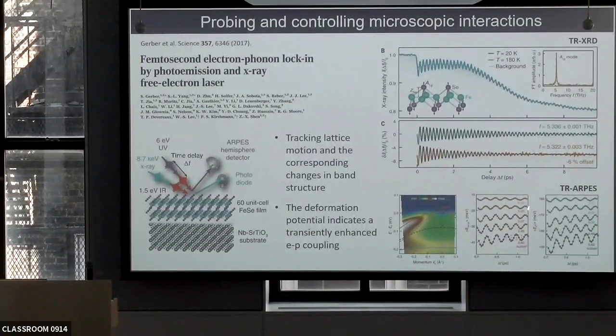So here now the modulation in these two plots of the bands at the gamma point, if you look at the frequency and so on, follows exactly the modulation of the Bragg peak in the X-ray diffraction experiment.